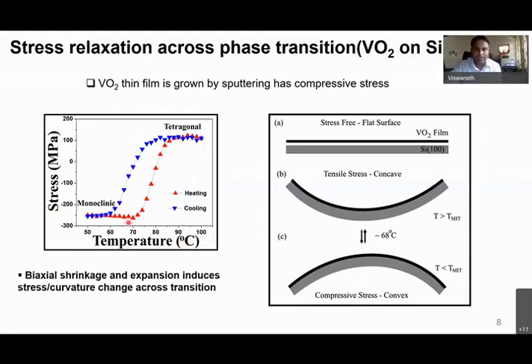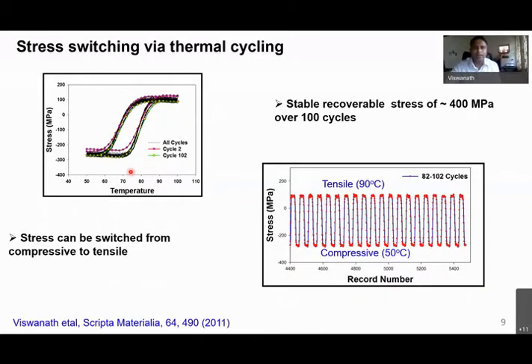You can see here the red marked triangles that correspond to the heating. Almost 300 to 400 megapascals of tensile stress is developed when it goes from monoclinic to tetragonal. And during cooling, it is perfectly reversible. So this is something known for a long time.